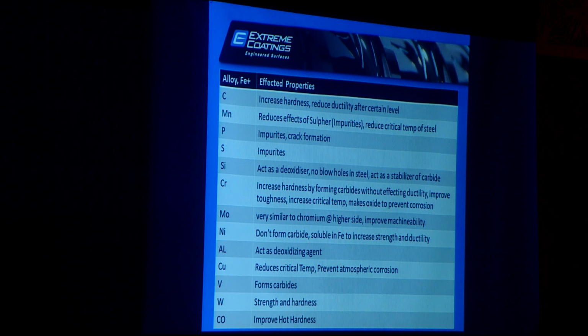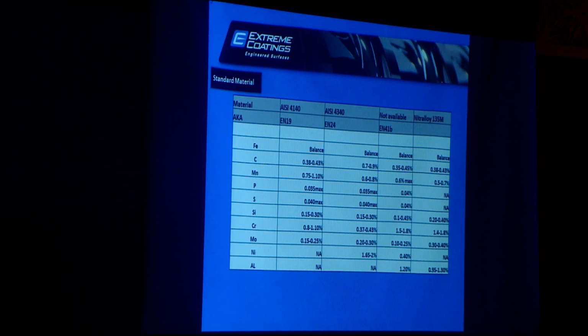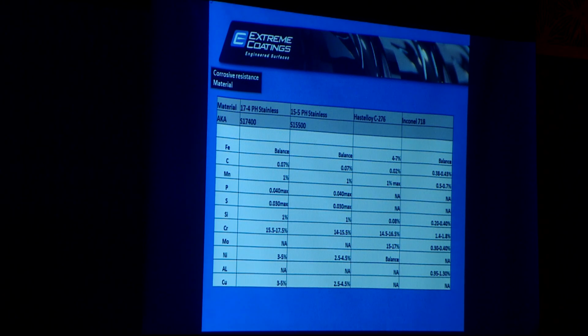So screw suppliers, when they select the steel for the screw and barrels, have to understand for which applications you are buying screw and barrels. Maybe the requirement is more on the corrosion side rather than the abrasive side. So the typical standard materials I mentioned, these are the four steels on which Indian suppliers will give a nitriding treatment, and they will give you the screw barrels. If you are having corrosive materials, then this is the chemistry of 17-4 PH and all those things. When I talk about this stainless steel, you can see that the percentage of chromium is more. That means it will give you more corrosion resistance. But at the same time, you have to sacrifice on adhesive wear as well as abrasive wear.